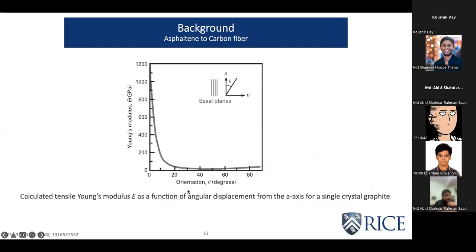Now, this picture will give you an even better idea. For example, for a single crystal graphite, when you have all the graphene sheets aligned, suppose this is the fiber and you are doing the tensile test along this direction. In this case, your theta becomes 0 because all the graphene sheets are parallel, or at 0 degrees, with respect to the stress axis. And if you are able to align all these particles along this axis, then you're going to get very high mechanical properties.